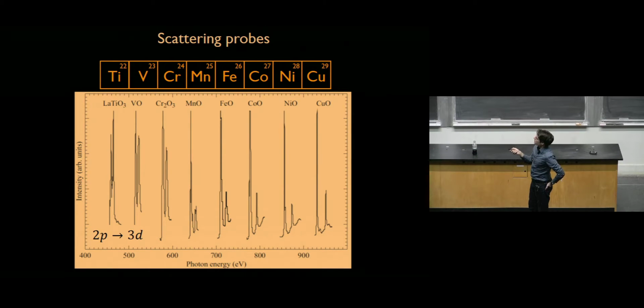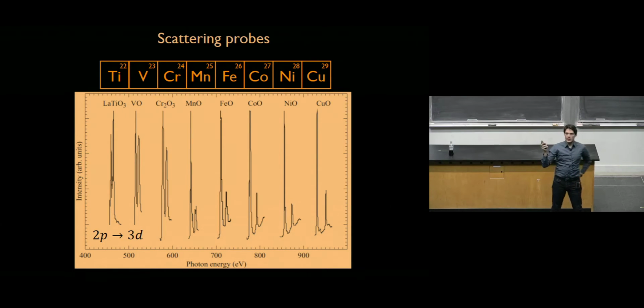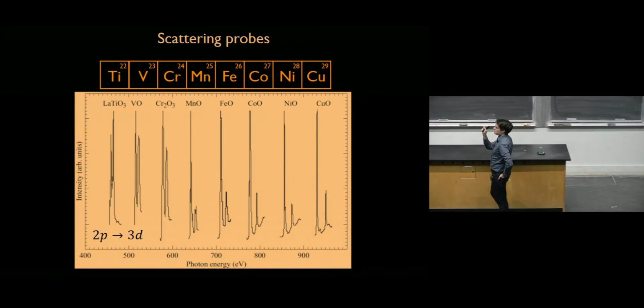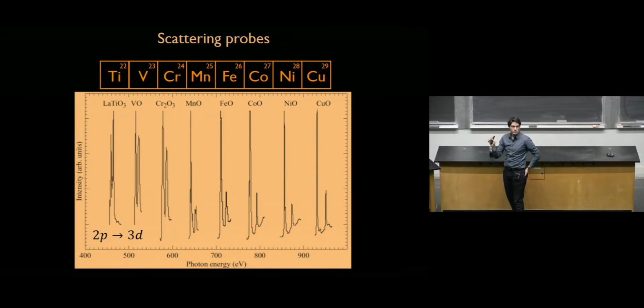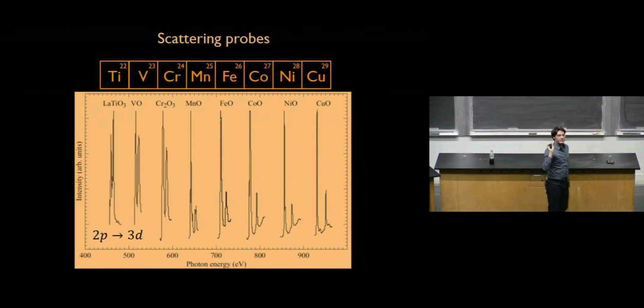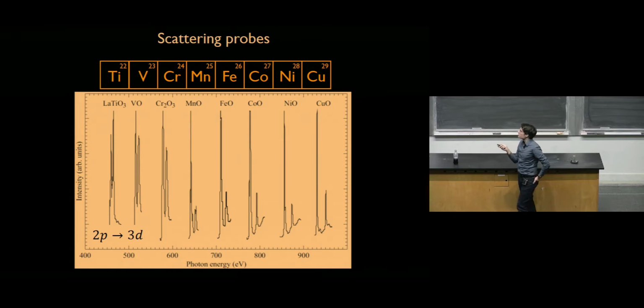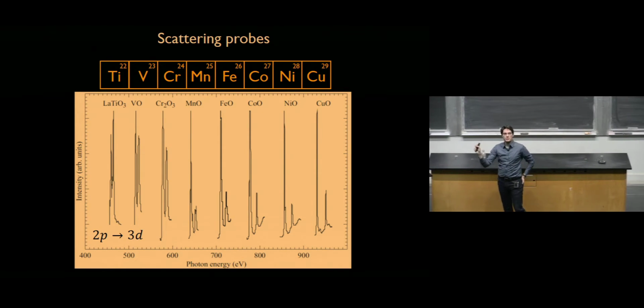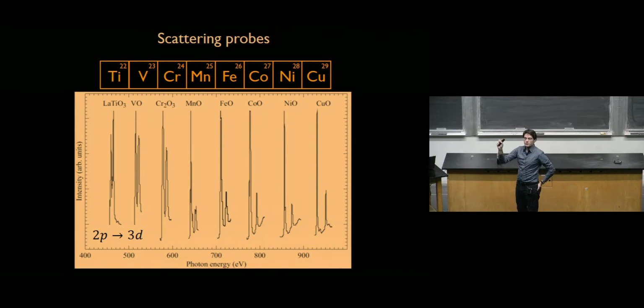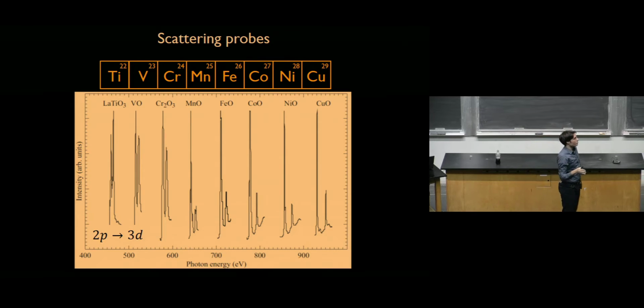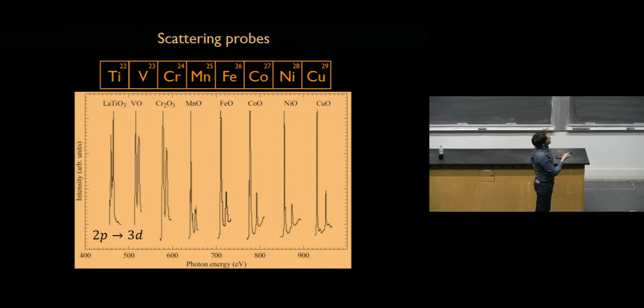So let's say copper. This is the energy for a transition between a 2p core level and a 3d valence electron. And if I tune my energy there, I increase my sensitivity by something which can be of the order of 1,000-fold to the 3d valence electrons of copper. If I go to nickel and I do the same type of transition from a 2p core electron to a 3d valence electron, then I'm looking at the same thing, but now the energy is slightly different because of the binding energy of the 2p core hole. The core electron is changed. So all of these different elements have different resonances that occur at different energies.